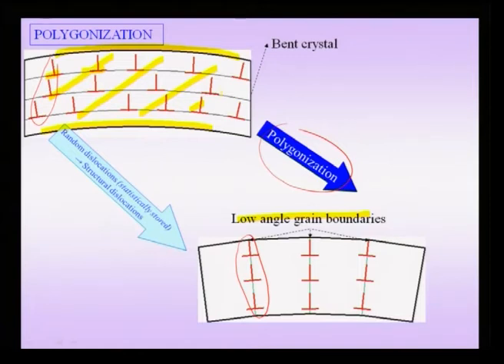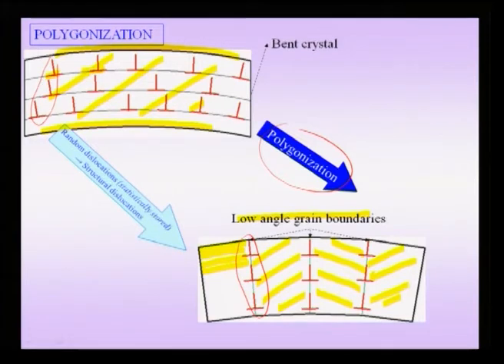This is now forming subcrystals. So, these are all now my subcrystals. This is subcrystal 1, then you may have subcrystal 2, subcrystal 3 and subcrystal 4. So, the original single crystal is now split into subcrystals, which have between them a low angle grain boundary. In this process, which is called polygonization, an important phenomenon which takes place is that these random dislocations, which are otherwise called statistically stored dislocations, become structural dislocations. We know that the role of statistically stored dislocations in plasticity is very different from those of structural dislocations, but in this process we see that random statistically stored dislocations by their motion and rearrangement become structural dislocations, and therefore now the material is split into subgrains and there are low angle grain boundaries between these subgrains.